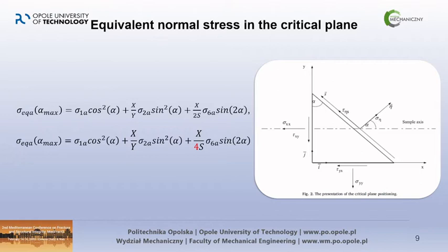After some analysis of the results, we have found out that if instead of dividing the last component by 2, we divided it by 4, we would have better results. So this is an empirical equation. We've found out that it could be a good solution to divide it by 4.